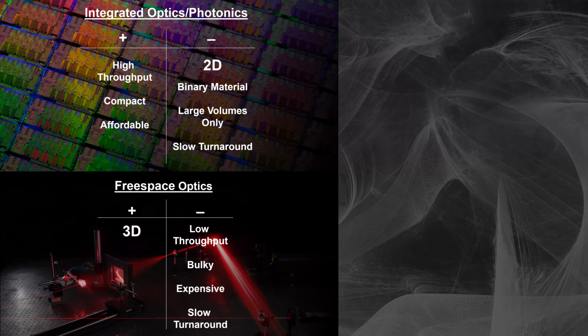But if you have photons in a waveguide and you want to go up into Z, something like that, you have a sharp right angle bend, you're going to lose pretty much all of your light. Right? So photons really want gradual changes, typically both in geometry and in materials. And here's another issue: typically it's binary patterning of material. You either have a material or you don't have a material. And so if you want to get smooth gradients of phase or index, you have to play a lot of difficult tricks. And then economically, it really only works for very large volumes and has a slow turnaround time, of typically months.